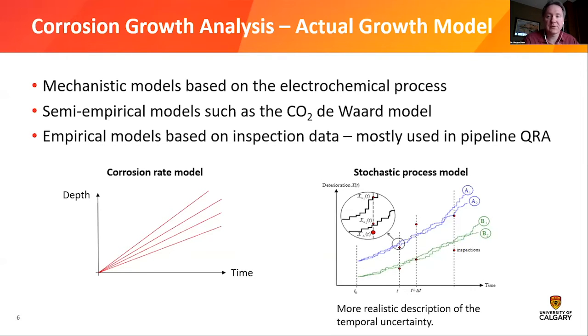Like so much percentage of wall thickness loss per year, and then you multiply it by the time interval, and that gives you the metal loss over a predefined time interval, for example. So if you use the corrosion rate model, and now because we want to explicitly model the uncertainties, we make the corrosion rate uncertain. So that means then we grow with different slopes here in that uncertain corrosion rate model. That is one way to go.